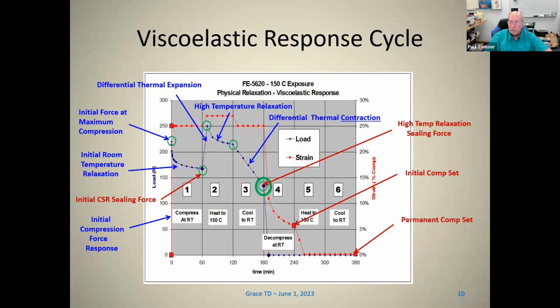This value is something you can test with discrete jigs by, after you do the initial sealing force check, putting it in the oven for 1 hour, taking it out, allowing it to cool, and then checking the sealing force again. So whether you do this continuously or with discrete jigs, as long as you follow these same positions, you should get the same number.